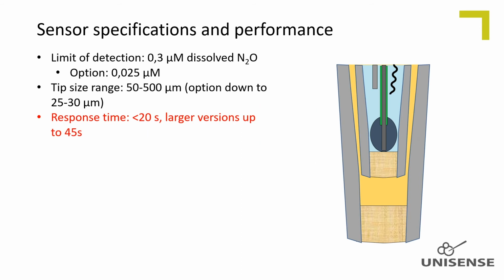The response time is a function of the nitrous oxide diffusion path length to the working electrode, and the diffusion path through the front guard makes it slower responding compared to other Unisense amperometric microsensors. The smallest sensors are made with a shorter response time, less than 20 seconds, whereas the larger and more robust versions have up to 45 seconds response time. Details on response time are found on our website.